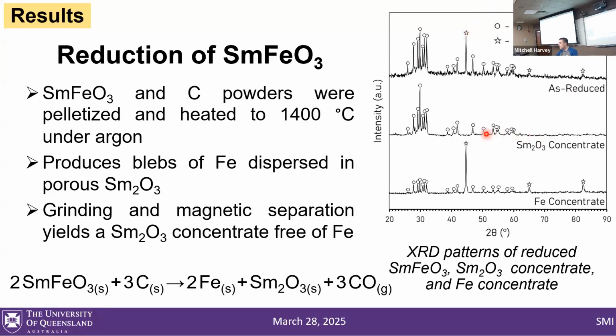And then our concentrate that we've done by grinding and magnetic separation, there is no iron peak. This main iron peak is completely absent in the samarium concentrate. And then the iron concentrate, we still have a fair amount of samarium oxide.